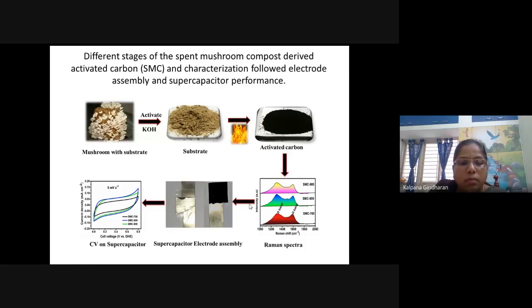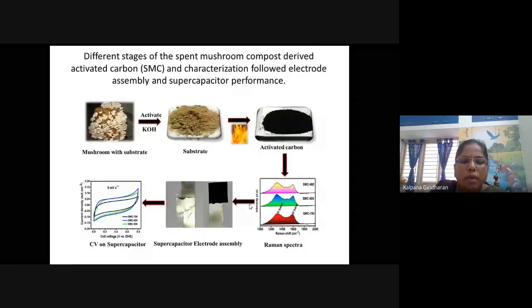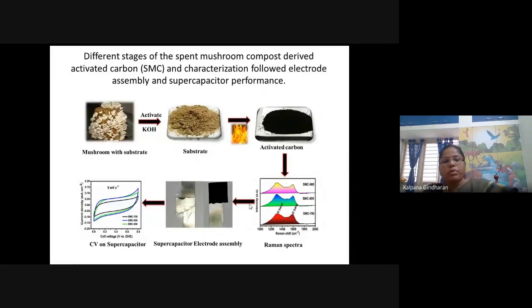We activated this carbon at 3 temperatures: 700, 800, 900 degrees Celsius, below which it was not a good proper powder, it was very sticky, and we faced some practical issues. So we optimized at 700, 800, 900 degrees Celsius, and achieved good performance with good surface area around 800 degrees Celsius activated carbon.